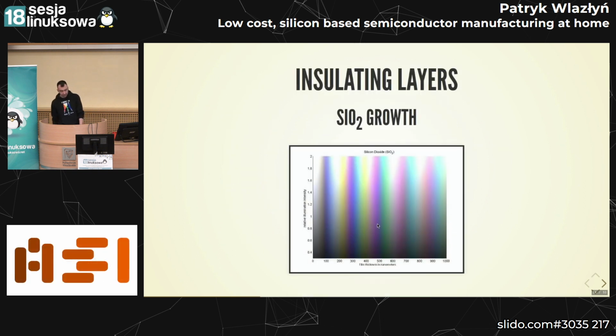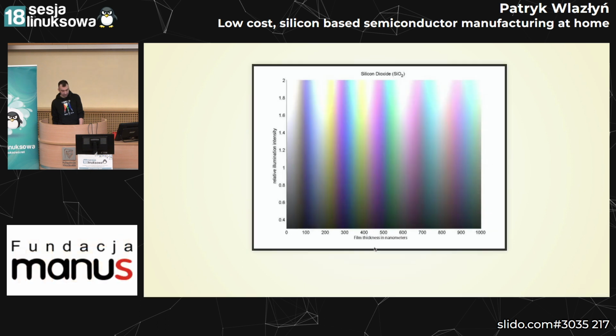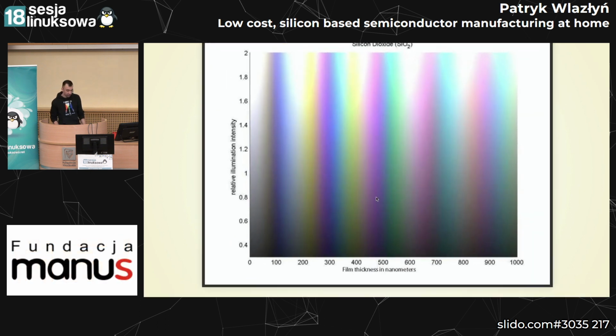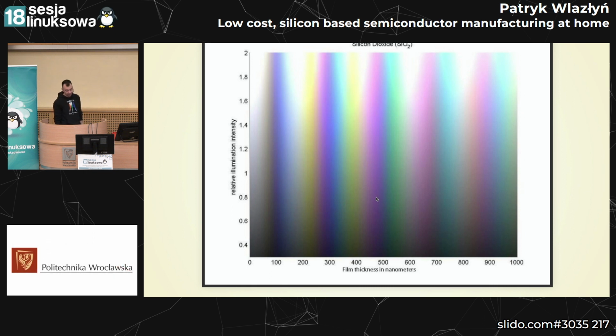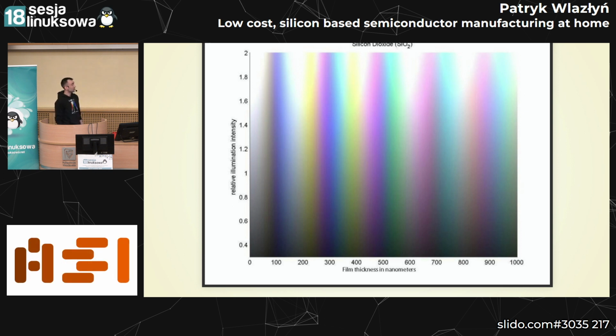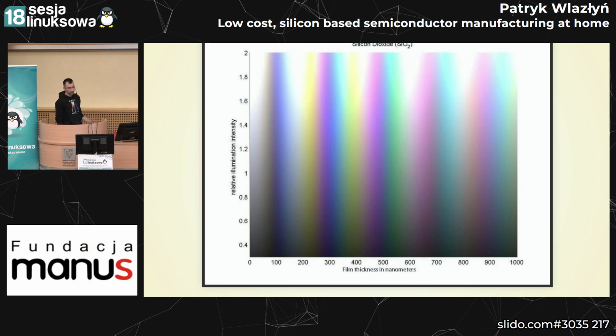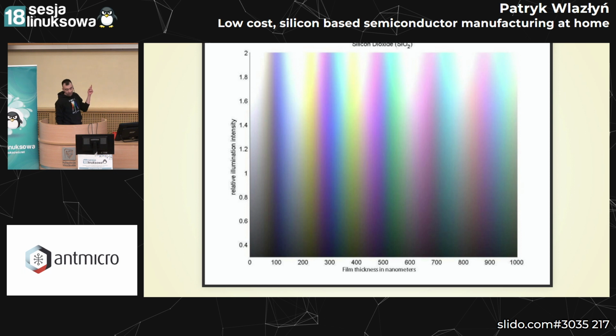And this is how you detect if your wafer has any silicon dioxide on top. This is a very useful thing for silicon dioxide, that for different thicknesses on the x-axis, we will see a different color with our naked eye. You can look at it and basically guess what kind of thickness you have. And different thicknesses are used for different purposes. For example, you can use the silicon dioxide just as an insulating layer between the silicon wafer and the phosphoric acid I was showing on the previous slide. But it will at the end also be used for a gate. And you can control how much voltage you have to apply to the gate by controlling how thick the oxide is.